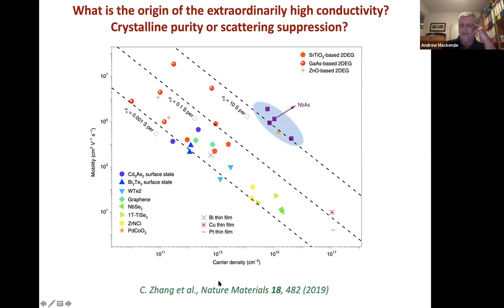And a nice way to frame it is this paper from another group, from Zhang et al., last year in Nature Materials. What they've been interested in was studying extremely high conductivity surface layers in niobium arsenide nanoflakes. And so they then did this big compendium of where do you see very high sheet conductivities in nature. And naturally, you see it in gallium arsenide-based 2DEGs. That's because of 30 or 40 years of extremely careful material refinement research. You then see it over a variety of surface states in modern topological materials, and as they're arguing here, best of all in niobium arsenide.